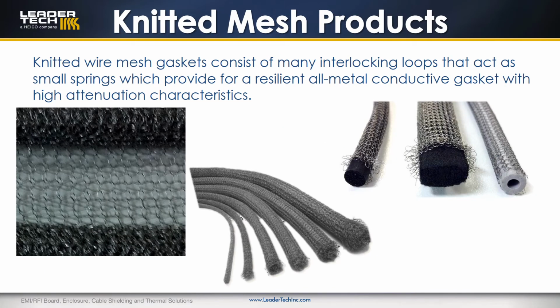Knitted wire mesh gaskets consist of many interlocking loops that act as small springs which provide for a resilient, all-metal conductive gasket with high attenuation characteristics. It can provide shielding effectiveness up to 130 decibels in the E field and up to 80 decibels in the H field. The standard wire materials are tin-plated copper-clad steel, Monel, and aluminum in cross-sections of rectangular, round, round with fin, and double round with fin. All cross-sections are available in both all mesh or elastomer core configurations.